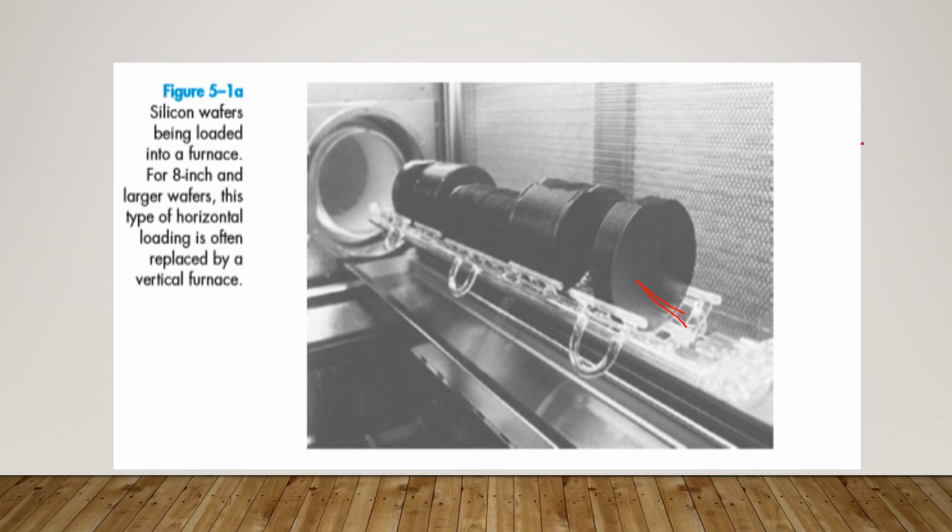It is important to remember the degree of cleanliness required in these processing steps. Since typical doping concentrations represent 1 part per million or less, cleanliness of impurities is critically important. So you always clean your push rod, your wafer holder, your wafer with the help of hydrofluoric acid before putting it inside the furnace.